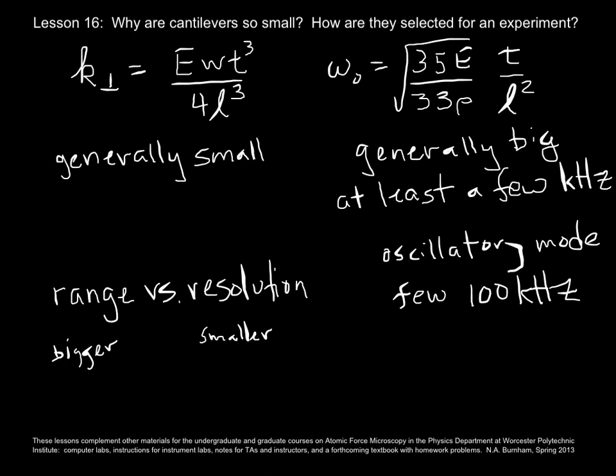Note that, in some sense, these two equations are diametrically opposed. For the spring constant, we generally want that small. For the resonant frequency, we generally want that big. And yet, in each case, the thickness is in the numerator and the length is in the denominator. And so when you're optimizing one, you're compromising the other. Fortunately, there's a wide variety of cantilevers on the market, and there's probably one that matches your needs. See you next time.